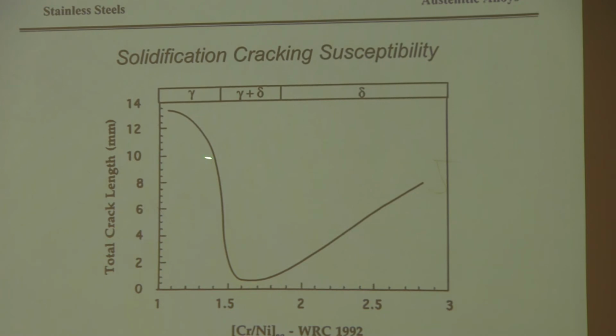And you'll see that when you get a value that's below about 1.5, you get much more cracking than when you're on the other side of that value of 1.5. In fact, you get a small region in here where you get very low crack susceptibility. And what this region up here is telling you is this solidified as austenite. Gamma is the symbol that represents austenite. Here is austenite plus ferrite, or delta, and then this is completely delta, completely ferrite over here.